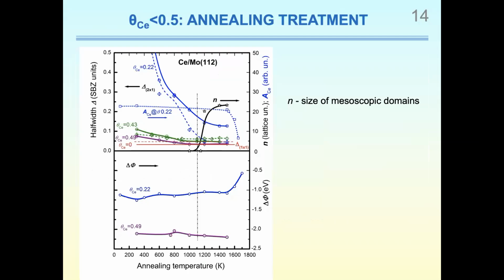Coming back to our annealing temperature dependence, we can see a rather sharp emergence of superperiodicity with period of 24 substrate cells at annealing temperature about 1200 Kelvin for coverage 0.22. It indicates that this temperature is critical for an irreversible transition from the simple primitive 2x1 phase to one-dimensional mesoscopic structure. Similar values of period and critical temperature were observed for all coverages less than 0.25, with coverage 0.1 being the lowest coverage at which spot splitting was visible.